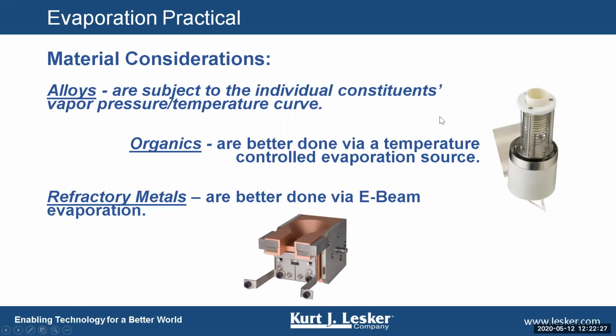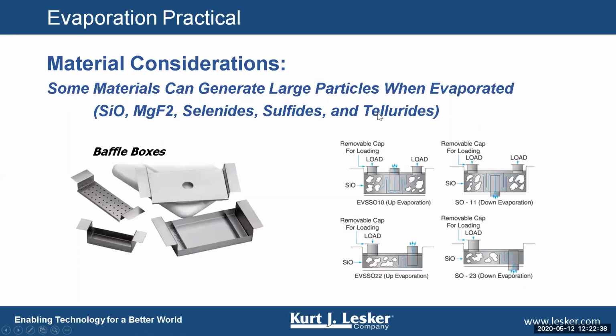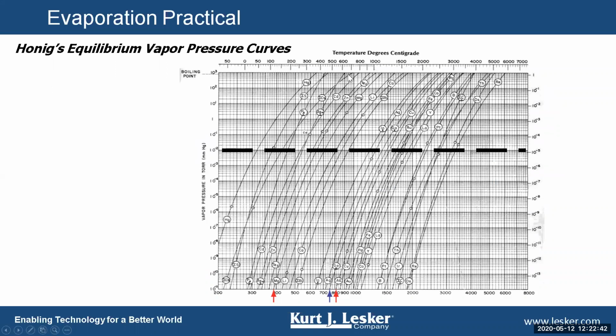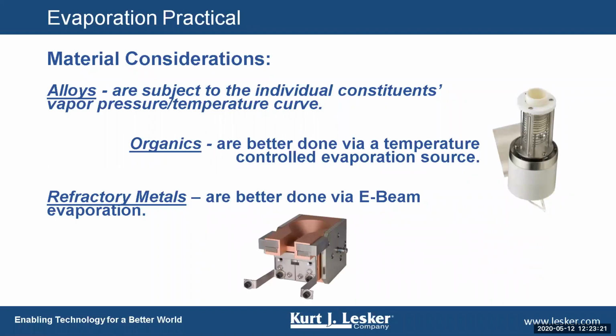Alloys, when you're thinking about evaporating alloys, they really don't work too well unless their vapor pressure temperatures are relatively equal. And by that I mean, if I go back two slides, if I can magically make an alloy out of, say, osmium and cadmium, if I start to evaporate that alloy, cadmium will start coming off at a temperature somewhere around 260 degrees C. Osmium is not even going to sneeze at 260 degrees C. So if you heat an alloy up like that, basically you'll get all the cadmium coming off and you'll be left with a clump of osmium. More or less that's true. There are some liberties taken there, but more or less that is true.